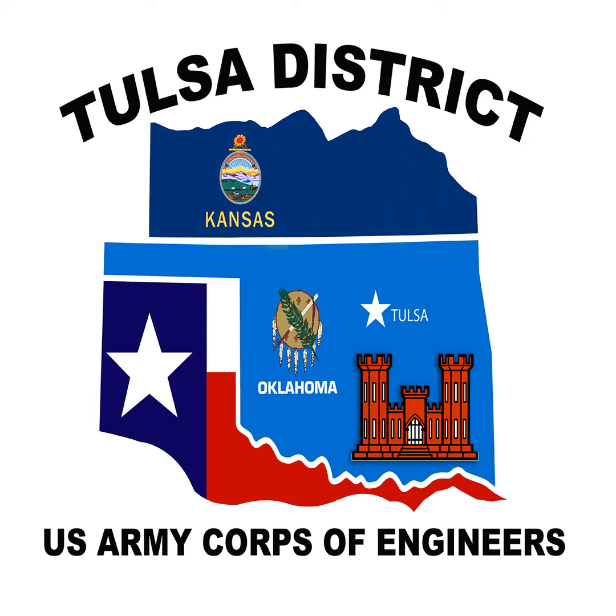Yeah, so there are a lot of bridges in Oklahoma, especially, that are reaching the end of their design lives, you might say. So they're 40, 50 years old. And a lot of those bridges have damage at the ends of the beams that result from being out in the weather for all that time, from de-icing salts coming through the bridge deck onto the ends of the beams. That causes the reinforcement to corrode. When reinforcement corrodes, it expands. It spalls off the concrete. So it blows chunks of the concrete off the beam.